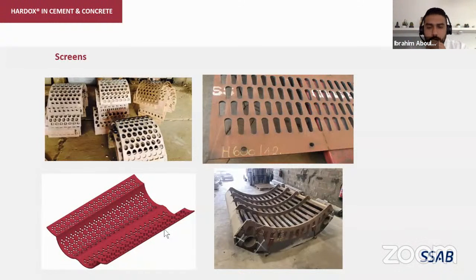If you don't have a laser cutting machine, or there's no facility around you that can do that, plasma cutting machine, high definition underwater, it can perform more or less similar, and Hardox can support you locally to define what is the cutting sequence that can be followed in order to avoid softening the small steel parts between the holes, which is the main issue when it comes to screens. Then we have the grizzly bars on the bottom right. The structural parts can be done from Hardox 450 or Hardox 500 Tuf, which are holding the grizzlies together. The grizzly bars themselves can be done from Hardox 500. Next slide, please.